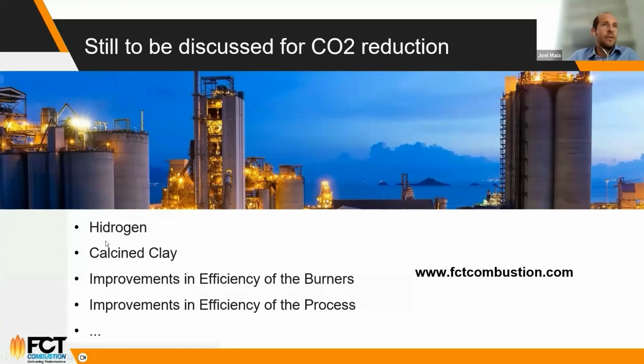Calcined clay, we as well, I don't know how familiar you are, but we can replace part of the clinker by calcined clay, and calcined clay has virtually no CO2, so you don't have limestone. You basically have an aluminum and silica compound, and this after heat treated, can behave similarly to clinker. And obviously, you can also improve efficiency on the burners themselves and in the process, and this will save your fuel independently of which type of fuel you're using, and this in turn will also improve the CO2 emissions. We are working on all of these areas and others, so please, you can check our website and you can see more details there.